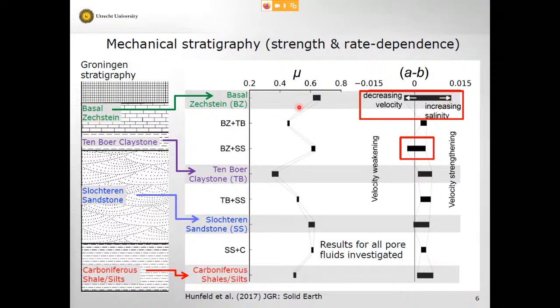What you see is there's a very marked mechanical strength stratigraphy. So the carbonates at the top are very strong. The Ten Boer material is very weak, this clay-rich material. The sandstone is strong, friction coefficient of about 0.6. Carboniferous is clay-rich, it's weaker again. So you see this stratigraphy and a mixture, for example, of this carbonate anhydrite rock with the sandstone, that's this one, it's also very strong.